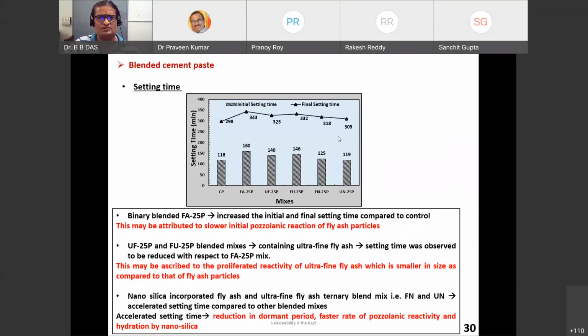The setting time also. Setting time is basically the control mortar, and we know that when we go with the secondary cementitious material, ideally, because of the slow pozzolanic reactions, the time will increase, isn't it? That is natural. But when you add just 2% nanoparticles, they are almost matching the control. Means there is no delay in the setting times. They are almost matching.